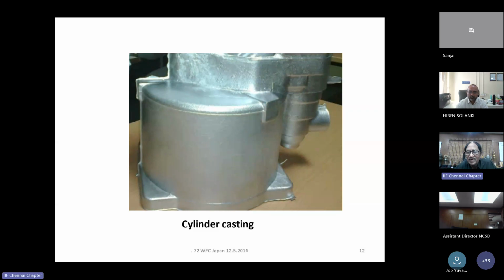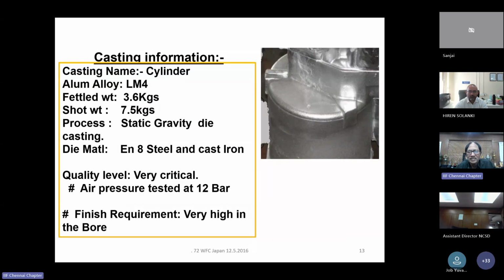This is one casting, a cylinder casting. It weighs about 3.6 kilograms, this is the fettled weight. Casting information: it is a cylinder, alloy is LM4, fettled weight is 3.6 kg, shot weight is 7.5 kilograms. The process is static gravity die casting. Die material is EN8 steel and cast iron, but the quality level is very, very critical. The air pressure test is at 12 bar. Finish requirements are also very high. Very critical casting.